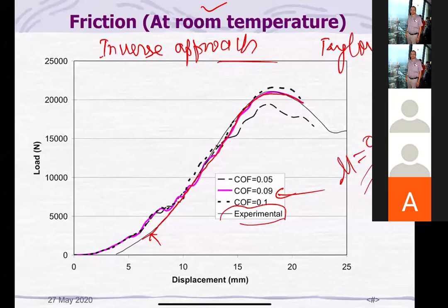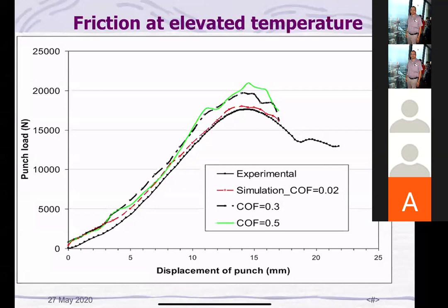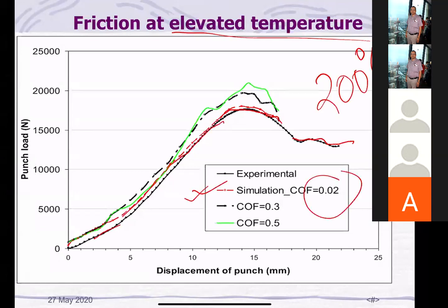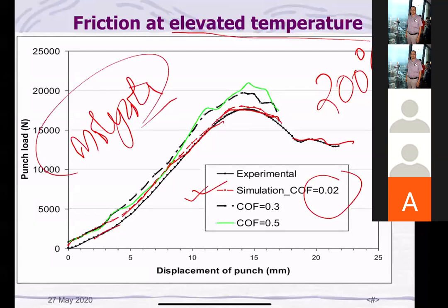Okay, now, but there are some errors in this process. You know why? Because we are taking so many assumptions here. Now at elevated temperature, I think I have taken 200 degrees centigrade for this particular case. This one is experimental, see red, black one line. So this coefficient of friction line almost overlaps. It means 0.02 almost overlaps. So we will say 0.02 is the coefficient of friction. But remember, at high temperature, we have used Molykote lubricant between the work and the die, because at high temperature, coefficient of friction is going to increase. So the only way we can decrease it is by using some proper lubricant.